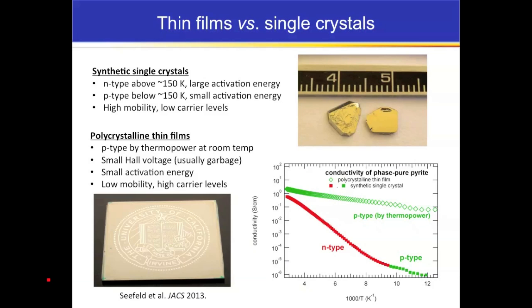The interesting thing here is to compare the electrical properties of the thin film pyrite and the single crystal pyrite. We see in conductivity plots, conductivity versus inverse temperature, 2 very different kinds of behavior. For the synthetic single crystals, what we find is that at high temperature, we have an N-type material with a large activation energy, a high mobility, and low carrier levels, like 10 to the 15 or 10 to the 16. The carrier type switches from N-type to P-type at low temperature. Okay? So this is a very uncharacteristic, strange thing for a semiconductor to do, and so we'll talk about this in a little bit.